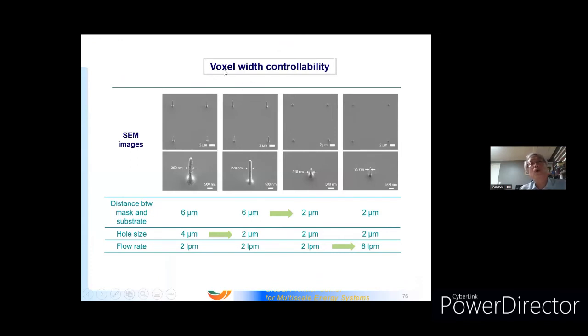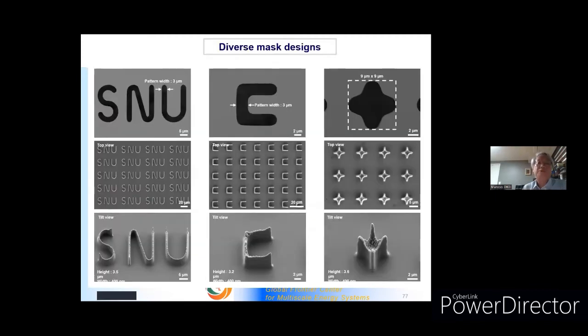You can also control the voxel width using control parameters. You can change the distance between mask and substrate, or change the mask hole size from 4 micrometer to 2 micrometer. You can change ion flow rate to increase focusing capability. Now you see 95 nanometer, sub-100 nanometer scale pillars using a 2 micrometer hole mask pattern under atmospheric condition. Or you can design a different shape of mask to fabricate a different shape of three-dimensional nanostructure, very compact structure, since we generate unagglomerated nanoparticles.